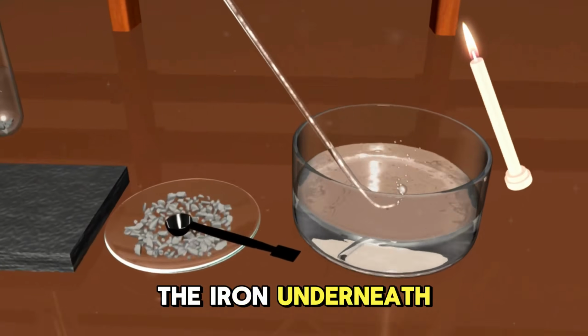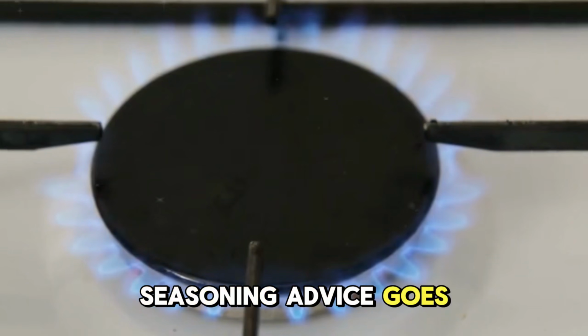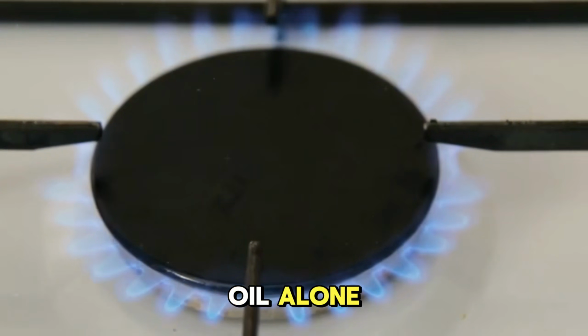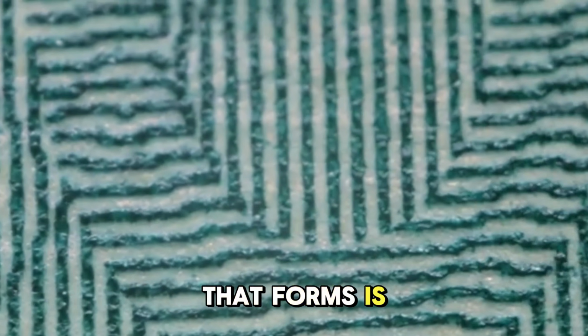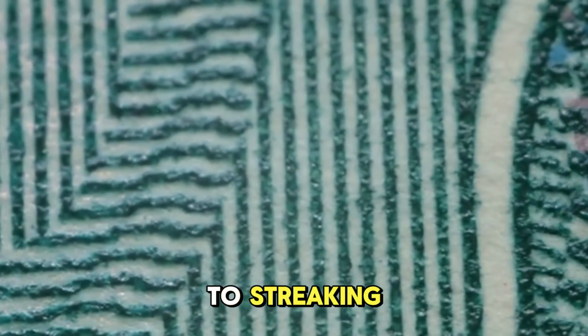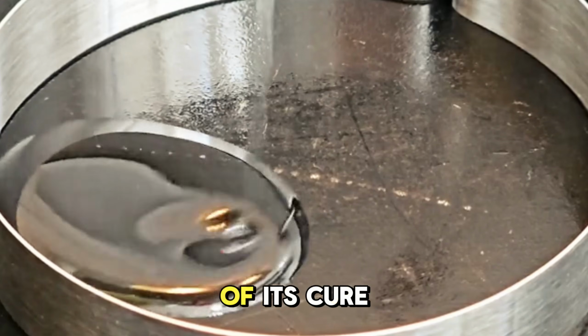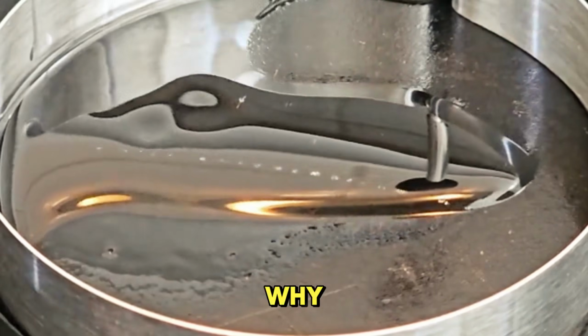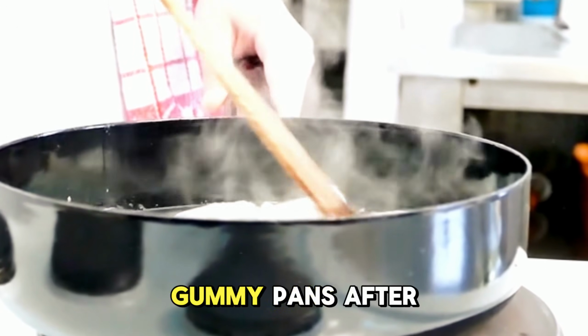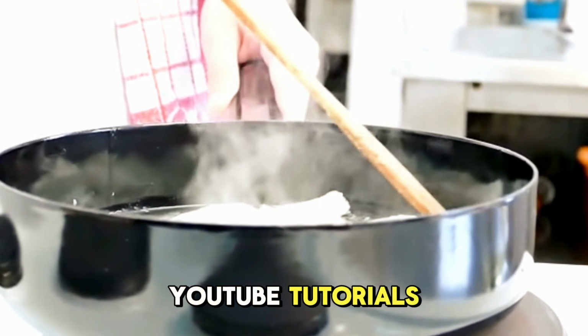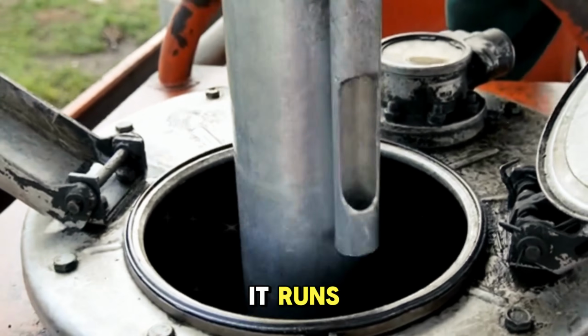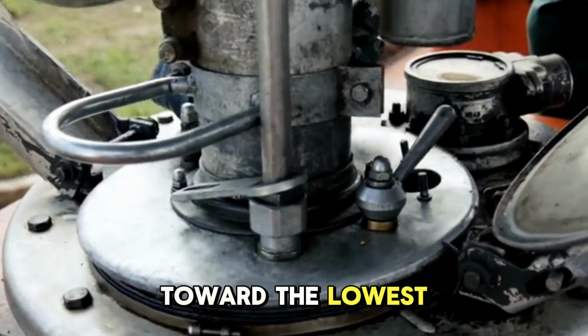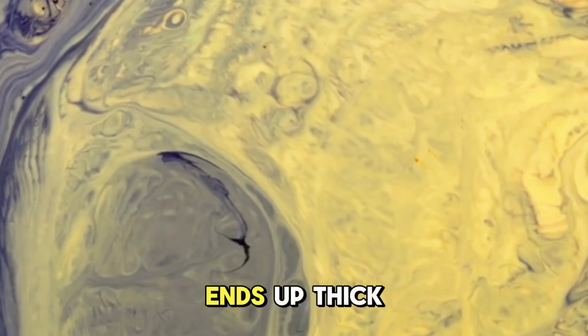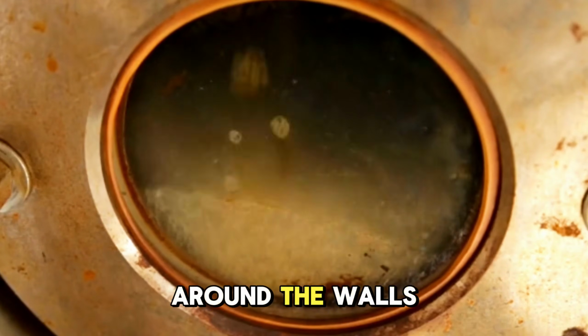Here's where most modern seasoning advice goes wrong. If you heat oil alone on iron, the polymer layer that forms is thin, uneven, and prone to streaking. It's sticky in the middle of its cure cycle, which is why so many people end up with tacky, gummy pans after following YouTube tutorials. The oil pools. It runs. Gravity pulls it toward the lowest point of the pan, so your seasoning ends up thick in the center and almost absent around the walls.